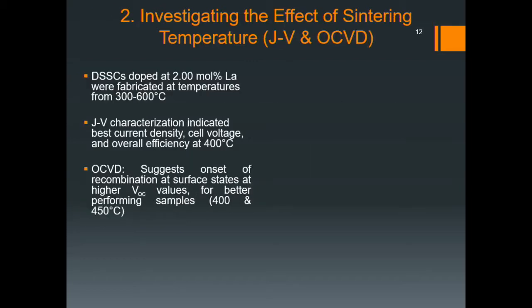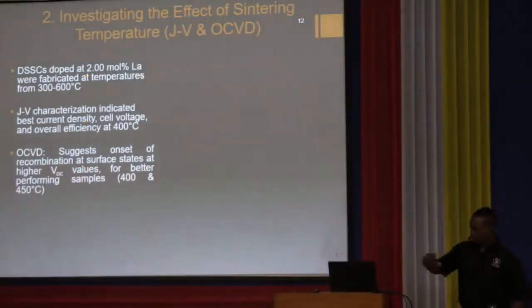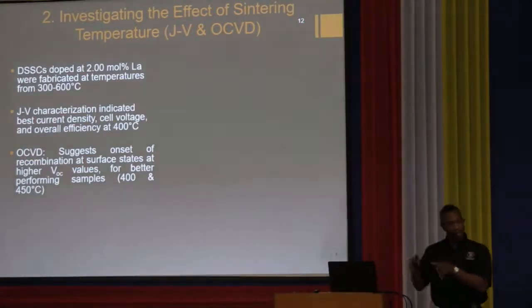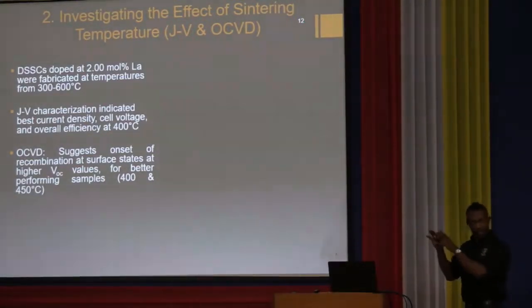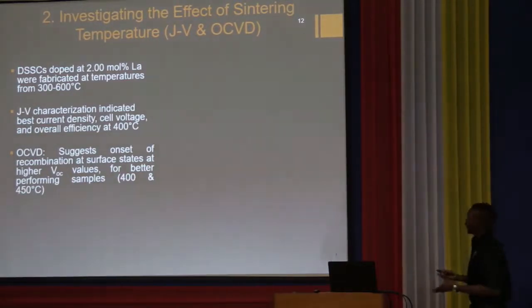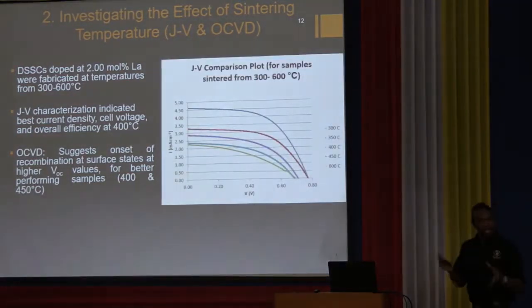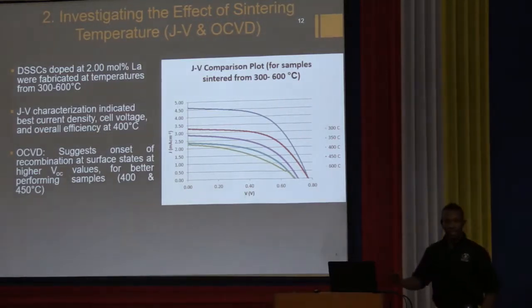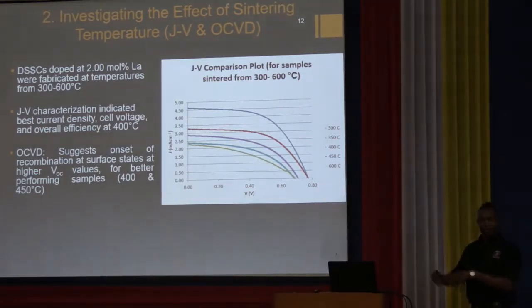So, after we investigated the effect of dopant addition, we took the best performing cell sample, which was lanthanum at 2%, and then investigated the effect of sintering temperature. So now what we did is we took this best performing cell sample and heated it at different temperatures. The heating is that final step before we begin to construct the cell. And we used temperatures ranging from 300 degrees to 600 degrees.